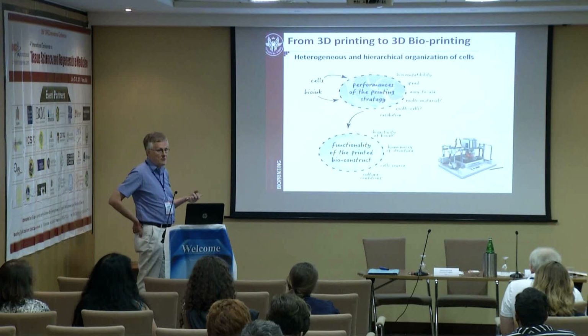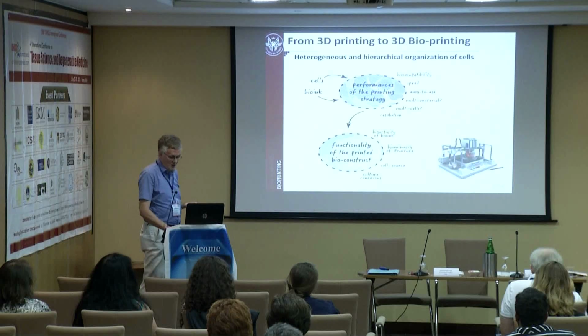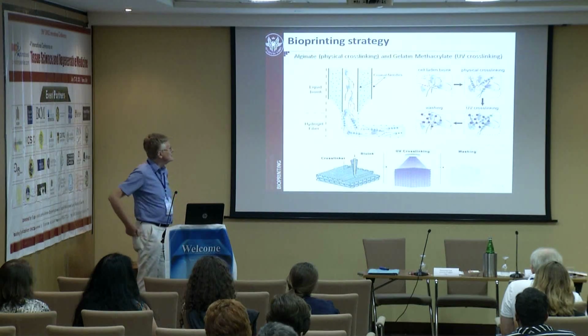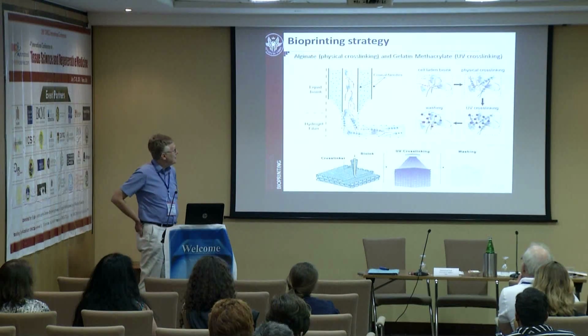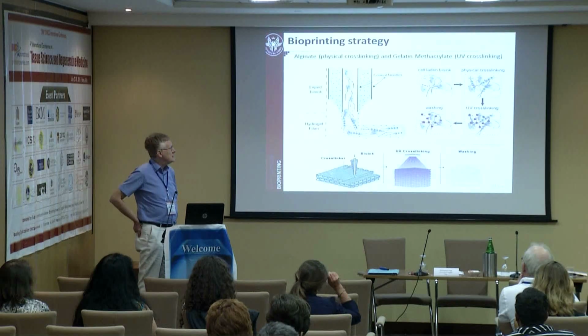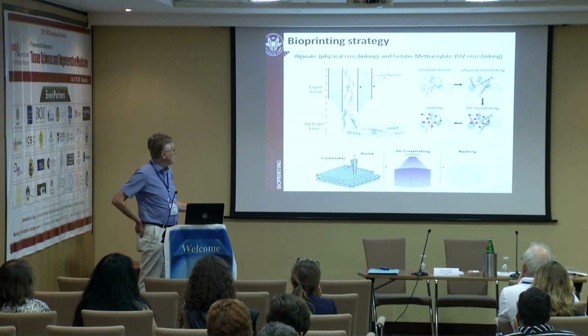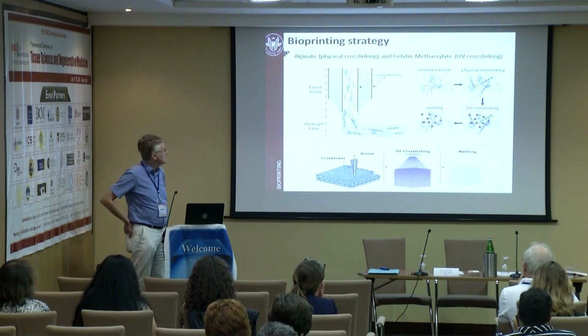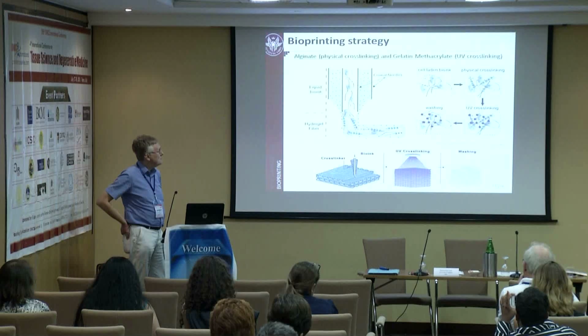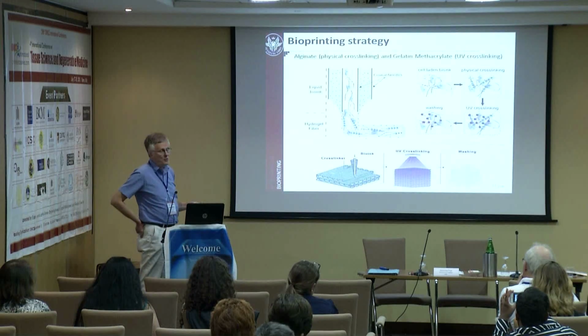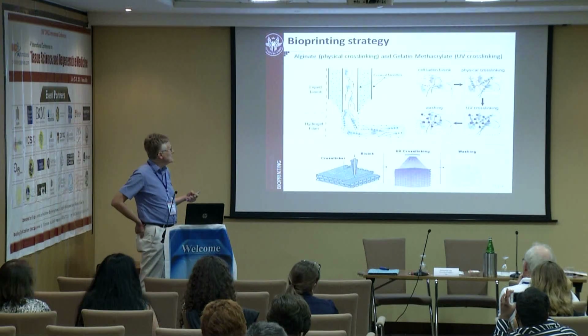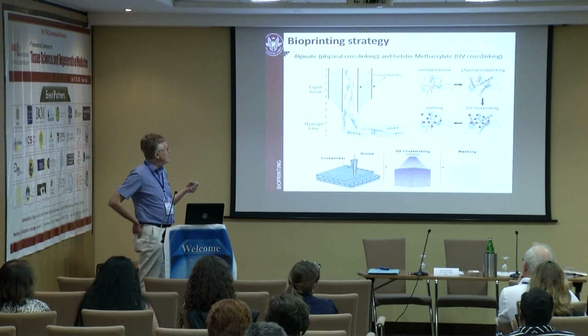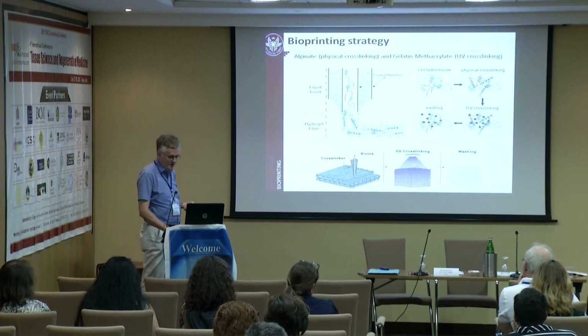Alginate is known to be biocompatible, but is not cell adhesive at all. So we thought to blend alginate with gelatin methacrylate. Gelatin methacrylate shows a strong bioactivity attributable to its abundance of integrin binding motifs and metalloproteinase degradable groups, which promote cell adhesion and migration through the matrix.